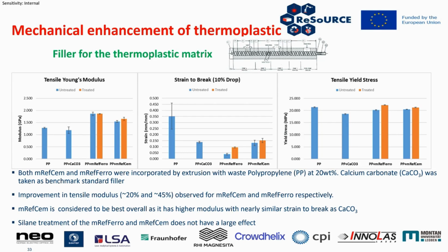As you can see there in the left-hand graph, we get about a 20 to 45% increase in the tensile modulus of the material. So it's making it stronger before it breaks. But on the next graph in, you can see that the actual strain to break is reduced, so they're becoming a bit more brittle in their application.